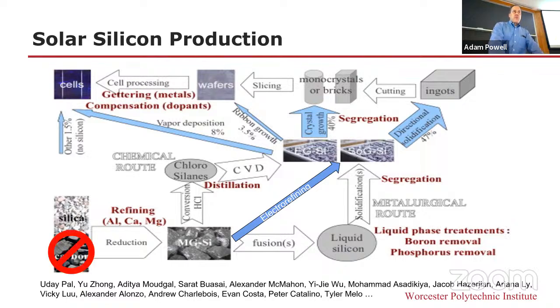But what if we could eliminate the carbon and just go directly from silica to a higher purity silicon? That a lot of the contamination comes from that carbon. We go from 99.8% pure silica to 98% pure silicon, metallurgical grade silicon, because of that contamination. And then we have to get that contamination back out again. So that seems kind of strange. Why not just go directly from silica straight to a higher purity silicon product?